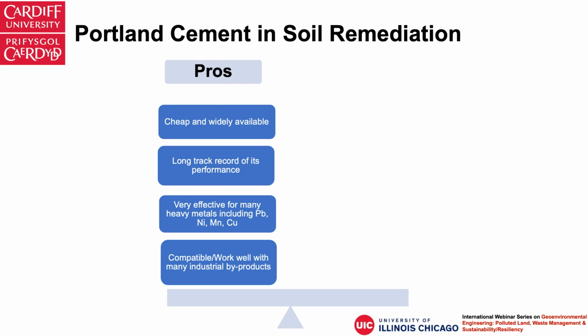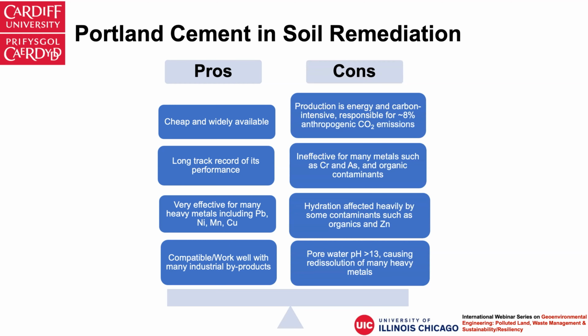Portland cement is also very effective at immobilizing many heavy metals, including lead, nickel, manganese, etc. And it is also compatible with many industrial byproducts, either as solidifying materials to treat these industrial hazardous materials, or just to incorporate them to improve the sustainability of the whole cementitious material. On the other hand, there are lots of cons as well. As I just mentioned, the production of Portland cement is highly energy intensive and also carbon intensive. It is responsible for around 8% of anthropogenic carbon dioxide emissions. And it is also ineffective for many other metals such as chromium and arsenic. These exist mainly as oxide anions in soils and in the cementitious materials. So they are anions and not very well immobilized by Portland cement.